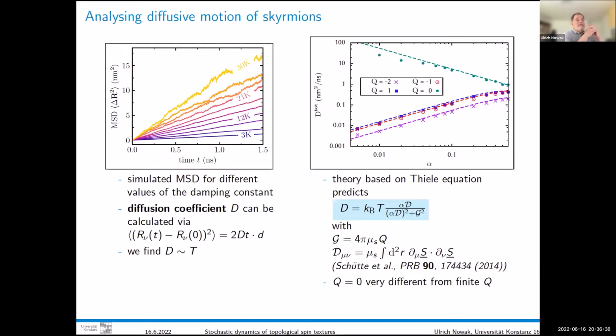So what can we do with that? Now we can simulate the skyrmions as I showed in the movies before. So we have this monolayer of iron. We take a large system, 10^5, 6, 7 spins. We have skyrmions in the model. We can define a center of mass, a position of the skyrmion, and then calculate, for example, the mean square displacement. And because of a finite temperature, or temperature dependent, that's shown here, they move diffusively. So the mean squared displacement grows linearly in time. That's what you expect for diffusive motion.